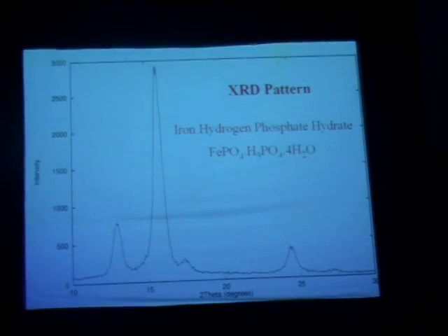You will notice phosphorus is relatively high in all the analysis of the iron pillar composition. There are other ancient iron objects, you can see phosphorus is very high. In the year 1997, I took a piece of rust from just below the Delhi iron pillar decorative bell capital, and subjected them to a lot of modern analysis techniques. And I found X-ray diffraction pattern, only one crystalline phase, which is a phosphate, only one.